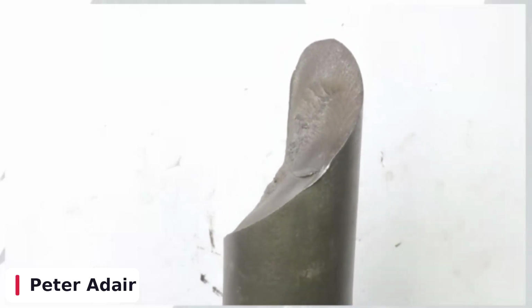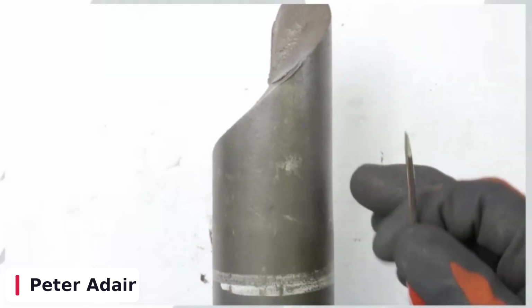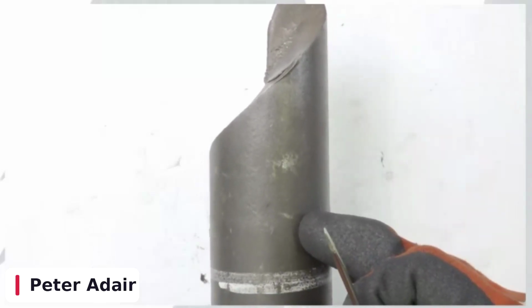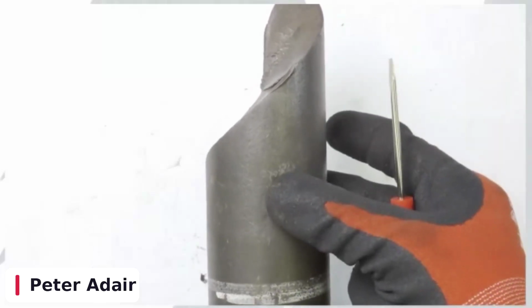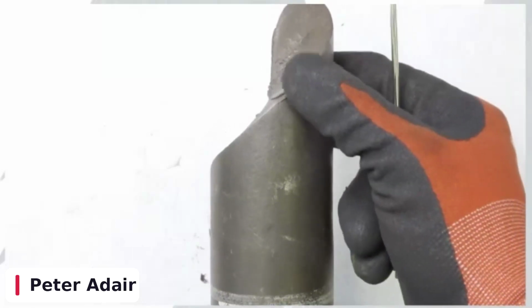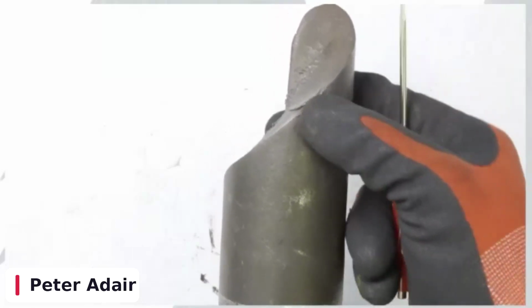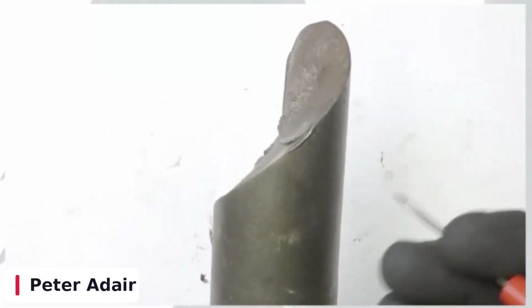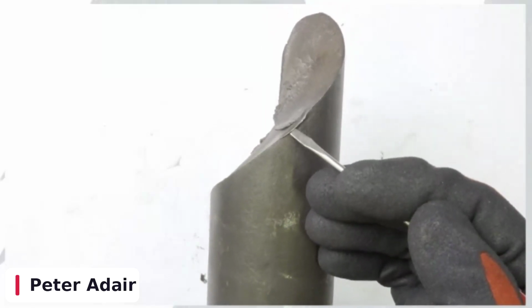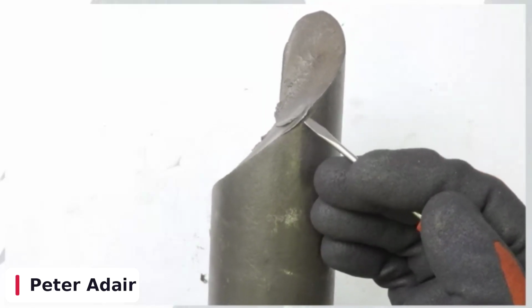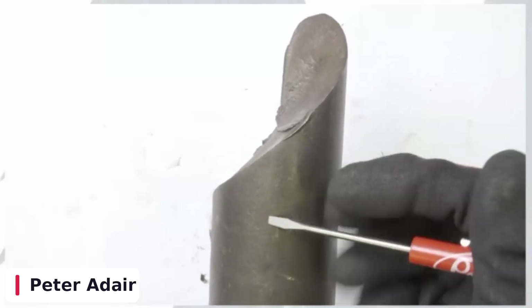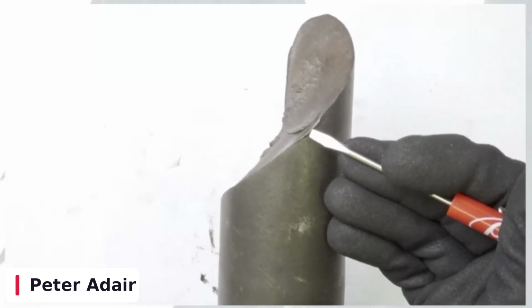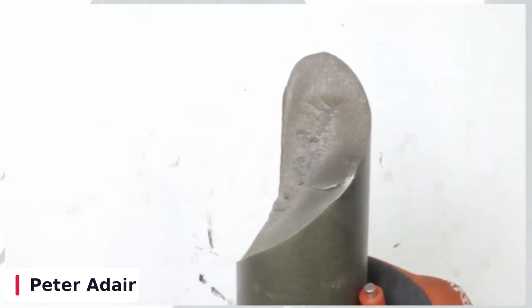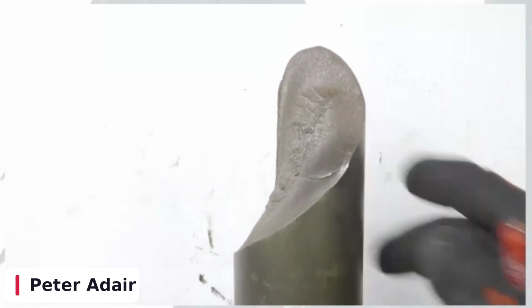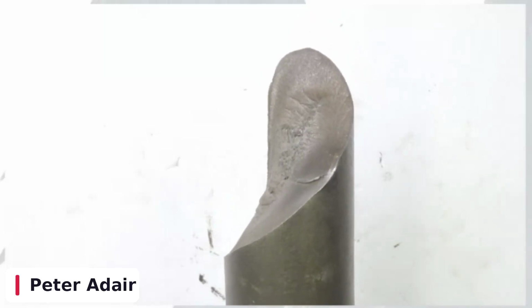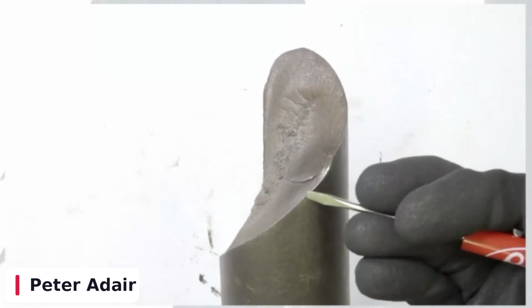Maybe you didn't know, but our shafts are not perfectly round. We shot peen them. So we take all the stress risers out of the surface of this shaft. And someone, whether it's a tow truck driver, a technician, a parts guy, somebody nicked this shaft with either the edge of a bench, the edge of a toolbox, a cutting wheel, something put a massive dent in this shaft. That little nick in the shaft, that little dent, is what caused this shaft to break. Because we just stuck it back in the truck. We didn't think nothing of it.